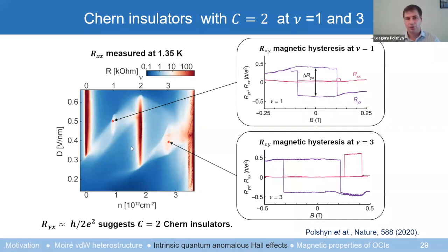Inside this larger halo, one of the symmetries is broken. It's essentially the valley symmetry. So the state is presumably spin polarized, this phase. And then inside the smaller halo, both spin and valley symmetry are broken. This is confirmed by the fact that inside these regions, we also can see some small anomalous Hall effect, which tells us that time reversal symmetry is spontaneously broken, not only at this state, but also inside this entire region.